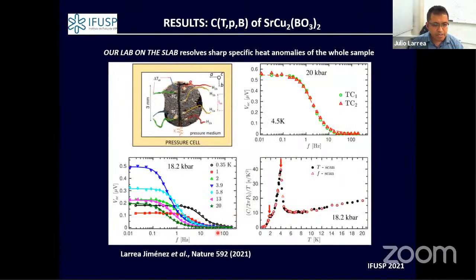Another interesting point is that we made measurements on different batches of samples to be sure about the reproducibility of our results. What we observed, for instance in this right upper panel, is that putting different modulated thermometers in different places, first of all, you obtain the same result.